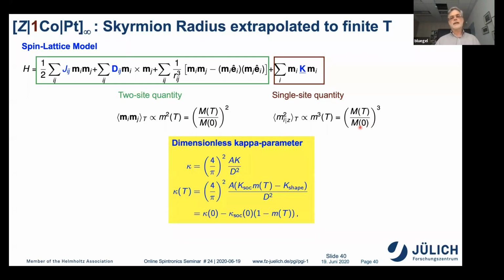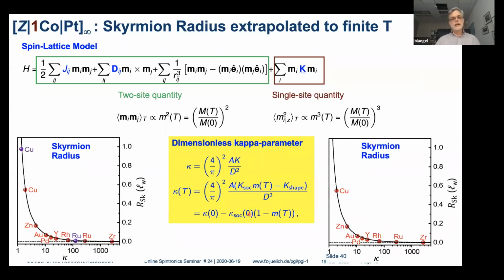And now if you put that into our kappa parameters, you see basically this magnetic anisotropy contribution, the spin orbit contribution to the magnetic anisotropy, scales differently than the rest. And that means my kappa parameter is becoming, as function of temperature, smaller. So that means if you look at the kappa values which I have shown you at T equals 0, here is an example for ruthenium and copper. You see ruthenium becomes a little bit larger because kappa becomes smaller, but copper is already on this strong rise. So a small change in this kappa makes a large change in this skyrmion radius.